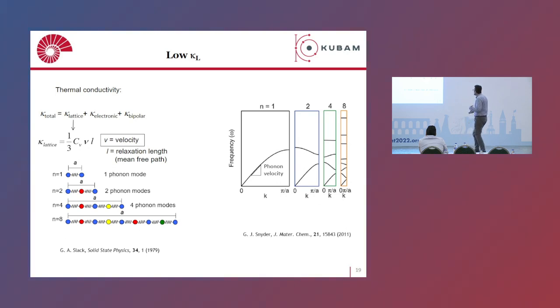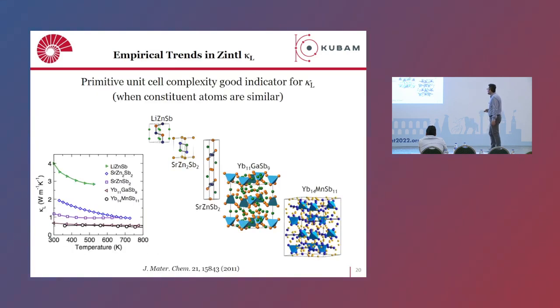In this way, if you increase the number of atoms, different types of atoms, you basically have larger unit cells, which leads to more low-velocity optical modes that substantially lower your thermal conductivity. This is nicely experimentally shown for a particular family of materials called the Zintl phase. You can see lithium zinc antimonide, strontium zinc antimonide, all the way to ytterbium manganese antimonide. The atoms are similar, but the difference is the complexity.